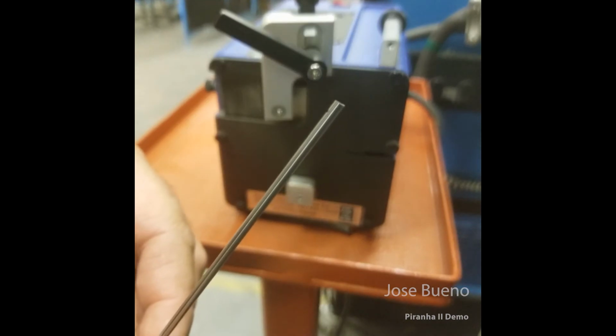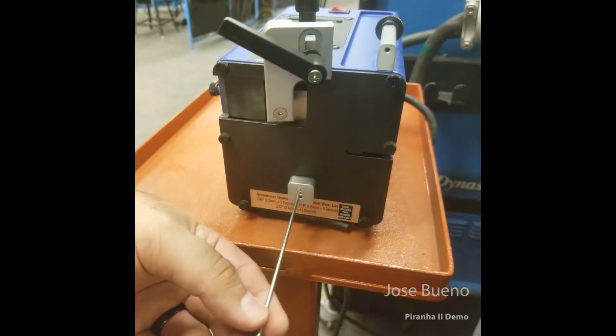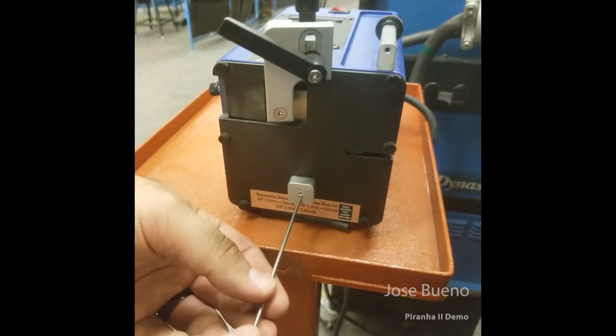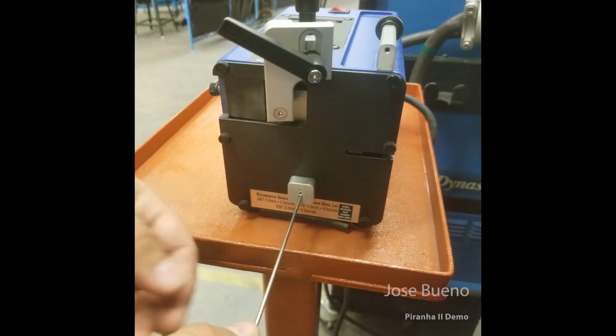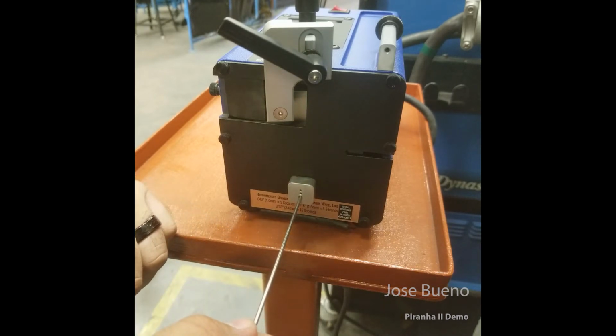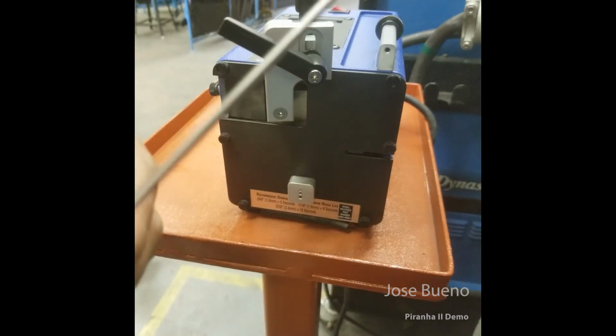Let it do the work for you. So just lightly make contact, listen for that grinding noise, and then slowly move the tungsten around in your fingertips. By sliding it around in your fingertips, this is going to prevent a burr from being created on one side of the tungsten. And this is also going to give you a nice, even grind.